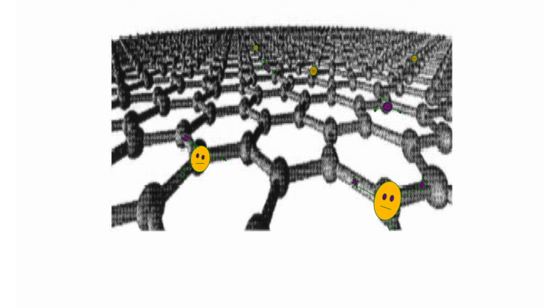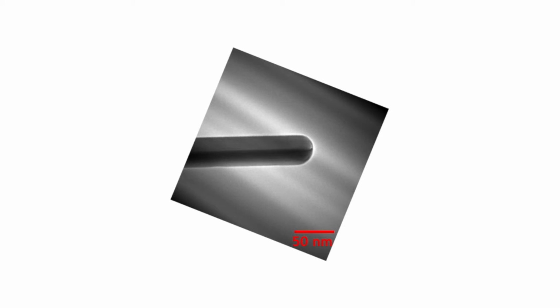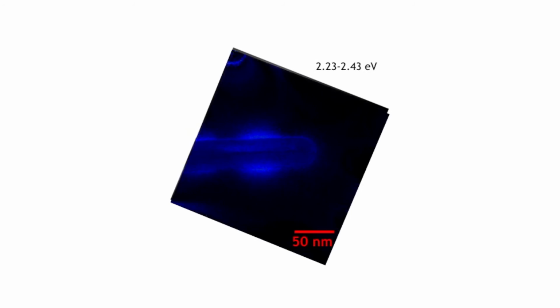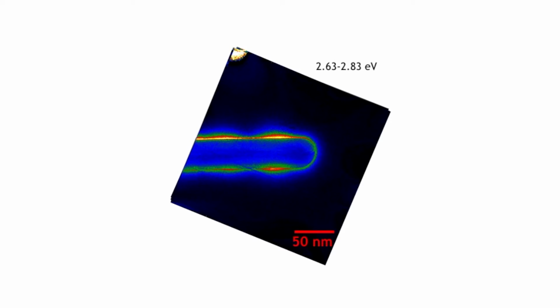So additionally to the atomic structure and the chemistry investigations on the atomic scale, we can furthermore interrogate with the electron beam nanoscale optical behavior of materials. And here we can see a silver wire that has light emission at around 3 electron volts in the blue and ultraviolet regime. And we can also see the pattern of this light emission. So with our new Titan Themis at UL,